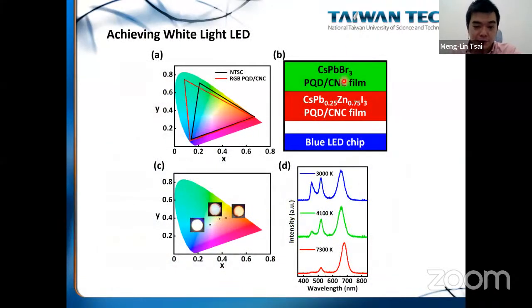Okay, and we can also combine the green and red films on top of a blue LED chip. And by placing different numbers of green film and the red film, we can actually control the color temperature of the white light. Okay, you see blue and red and green provides you the white light, right? But by controlling the numbers of films, okay, we can actually control the color temperature for the white light.